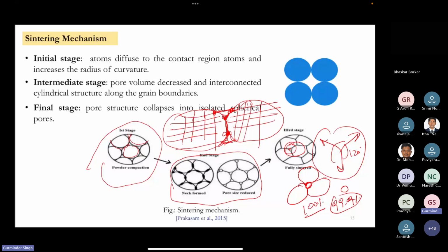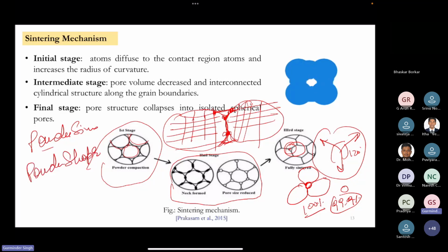It depends highly upon the powder size and powder shape. When you have a very large powder size, it will be cheaper. When you have a very small powder size, like nanoparticles, it will be more costly, but these are more effective. And the powder shape should be more spherical. I hope everyone knows why we need a spherical particle for sintering, because it has high surface energy and surface area, to transfer the energy to the nearby spherical balls.